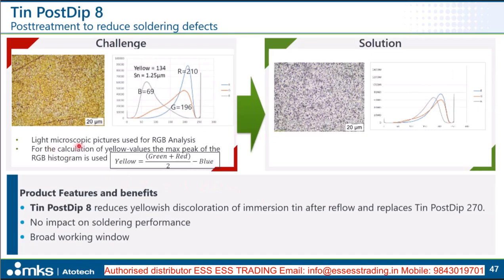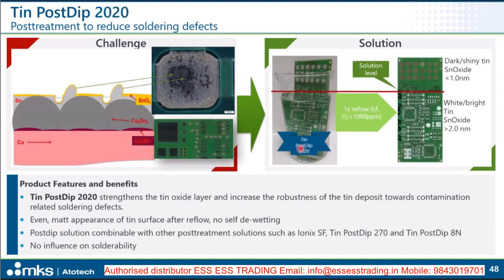This one is actually to prevent yellowish discoloration of the immersion tin layer, which may also happen after the reflow aging. And it's actually an inorganic kind of additive, which is applied on the tin surface and which is actually removed in the soldering process. It does not impact the soldering performance of the tin layer and can also be applied directly in the existing processes. And finally, the tin post-dip 2020.